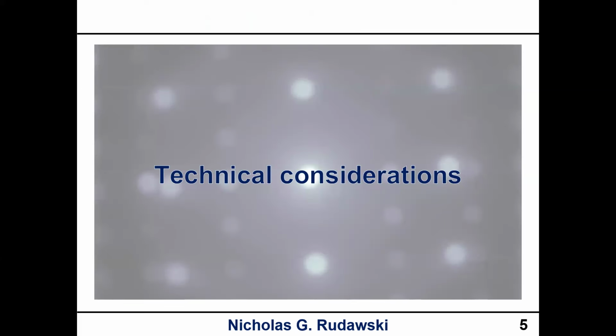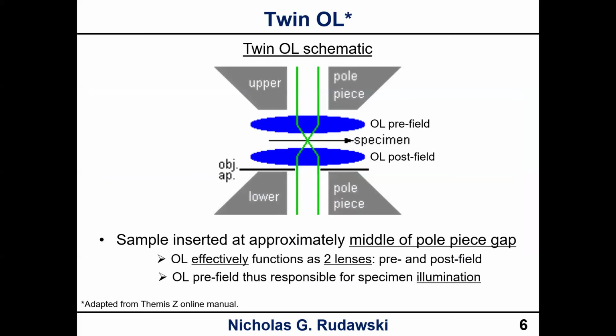Okay, so now if we talk about the technical considerations, on current state-of-the-art S/TEMs, they have a twin objective lens design. This was a schematic that I adapted from the Themis Z online manual. You have an upper and a lower pole piece, and you insert the sample at approximately the middle of the pole piece gap. In this case, your objective lens functions as two lenses, a pre-field and a post-field. Sometimes you also hear these referred to as upper and lower objective lens. But in this case, we're concerned with the pre-field because that is the last lens that the beam sees before it illuminates the sample. So that is responsible for specimen illumination.